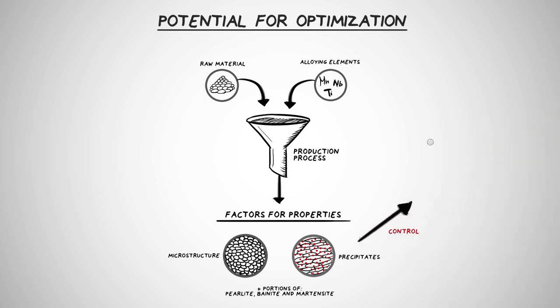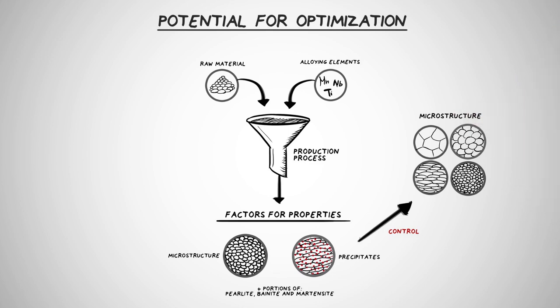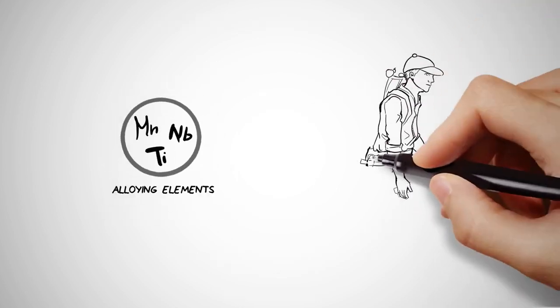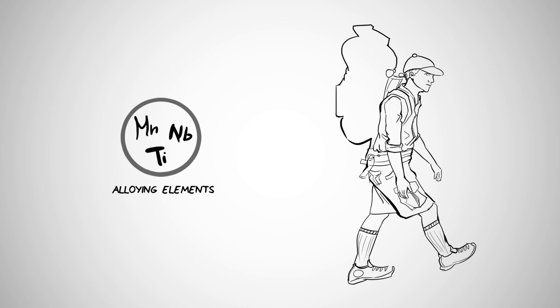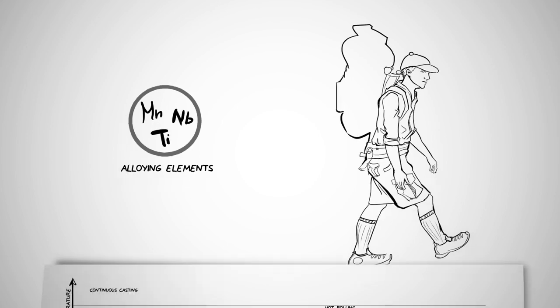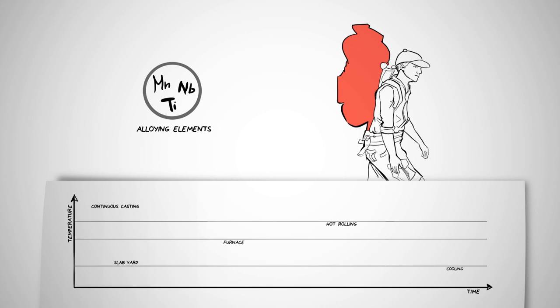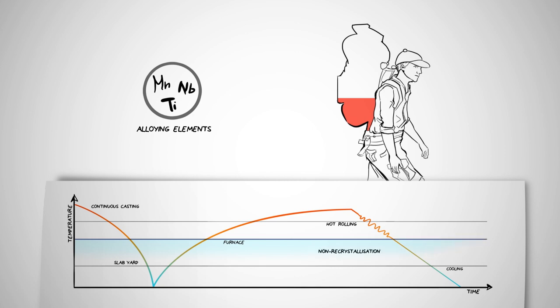Precipitates are needed to control microstructure evolution during rolling and for the precipitation hardening of the finished product. This requires a sufficient amount of alloying elements in the solution such as niobium prior to hot rolling. Alloys resemble a lunchbox for a hike, which is given to the steel for its processing journey. The consumption of the packed lunch depends on temperature. For just as sandwiches are eaten during every break, each time the temperature drops, for example when the slabs cool, microalloys are gobbled up. In addition, should the temperature fluctuate during slab-by-slab rolling, it's essential that a finishing mill entry temperature below the non-recrystallization level is nonetheless guaranteed.